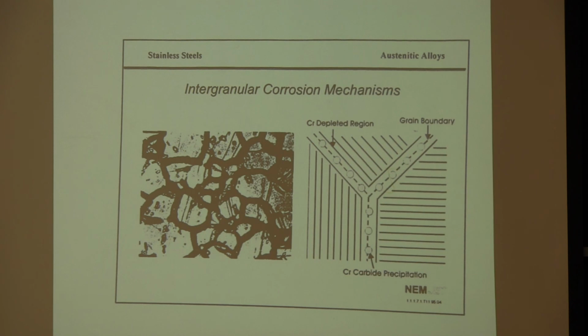The reason that happens is when you heat the material due to welding or some other reason, along the grain boundaries, you've actually got carbide precipitation that happens between the chromium and the carbon that's in the material. And when that happens, it leaves this chromium depleted region